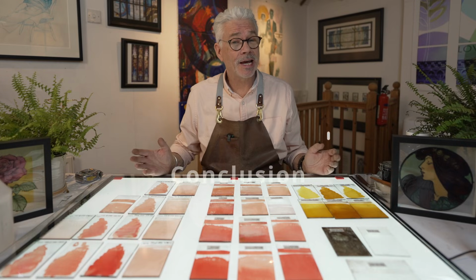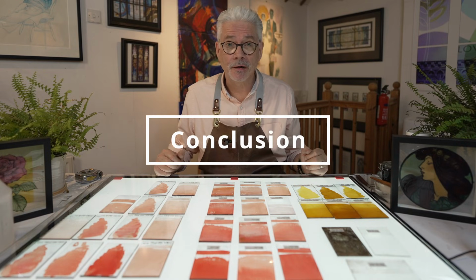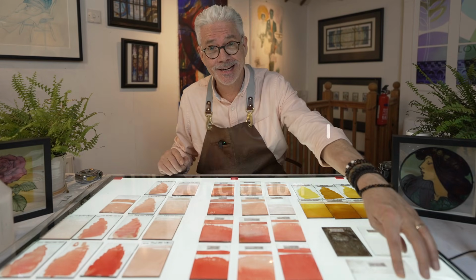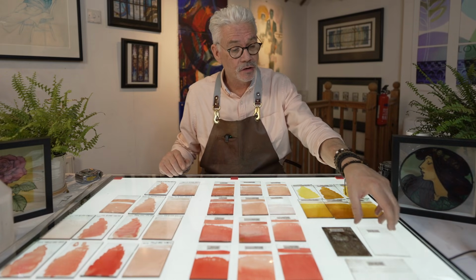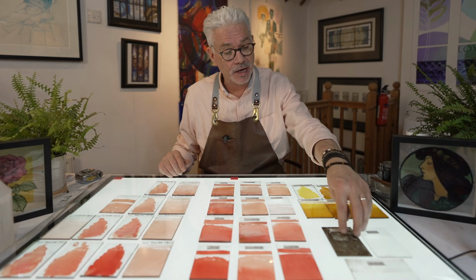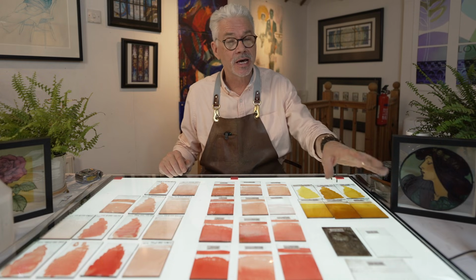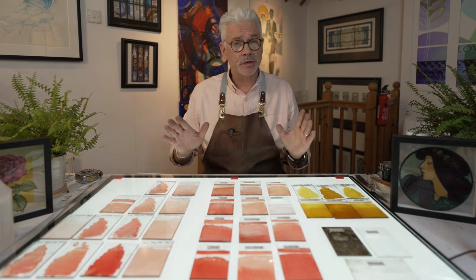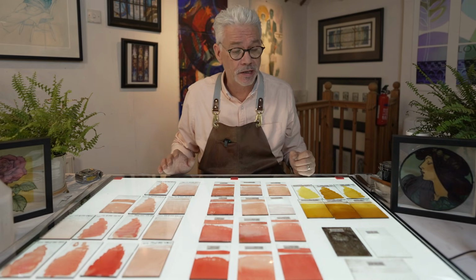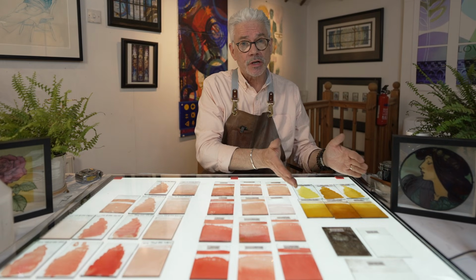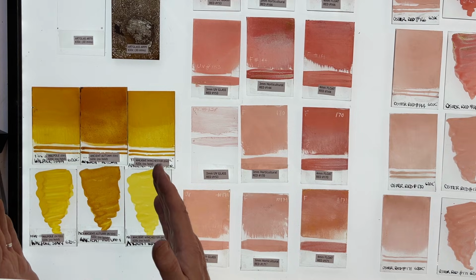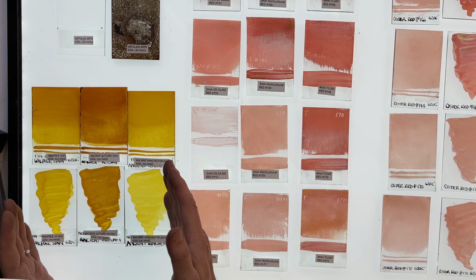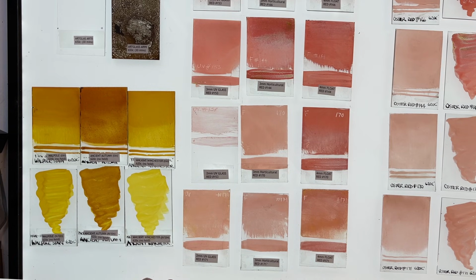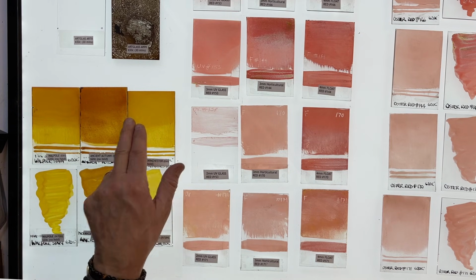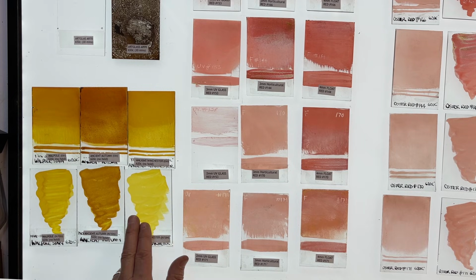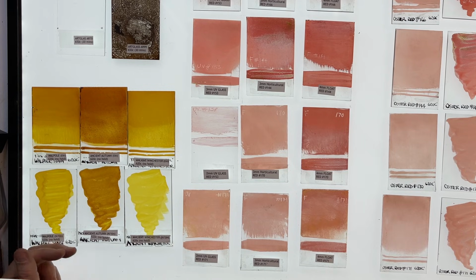So what's the big takeaway from these experiments? Well, firstly, don't use Bullseye Tekta, it doesn't work, and don't use the AR70 or the AR99 art glass. They have coatings on them which don't take at all well to being fired in the kiln. As far as the yellow silver stains are concerned, these tend to perform extremely well here, whether it is the tin side, which is this top row here, or the non-tin side, which is the bottom row. You can see there's a slight change in color.